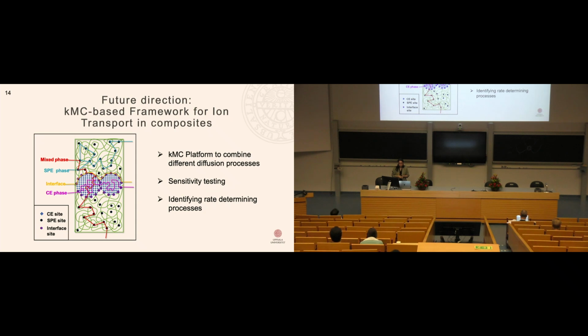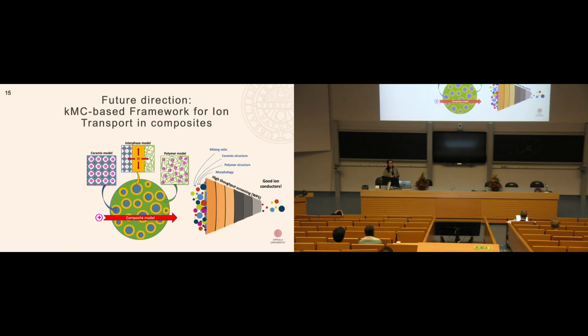And what we hope to accomplish in the future is to build an adaptable multi-scale and multi-phase modeling framework that can combine the dynamics of different phases into a mesoscopic transport model, where we can also test the sensitivity to different variations in the material in a pretty straightforward way, and identify different rate determining properties without actually knowing the true processes beforehand. Then the idea is that we can systematically study the mesoscale diffusion processes throughout the complete composition of multi-phase composite materials in order to understand how to design the optimal electrolyte material.